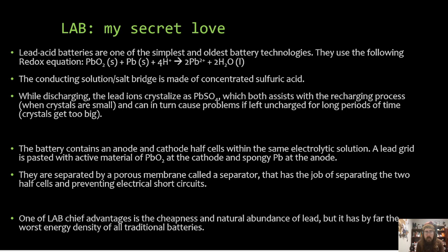Now, there are certain things that help and hurt. For example, lead sulfate is not super duper soluble, and so we will form crystals of lead sulfate as the discharge occurs. Typically we have a lead grid, and we've pasted the active material onto this lead grid, and so as it discharges, it forms lead sulfate crystals onto this grid, and it gets held on, kind of like a webbing.